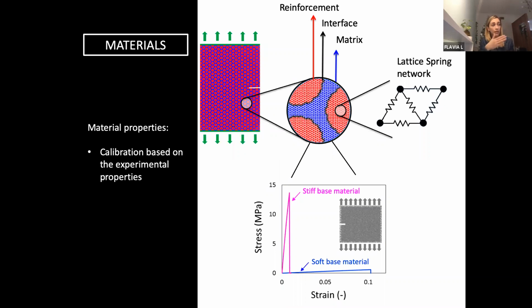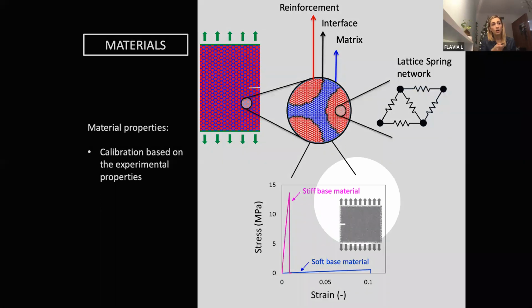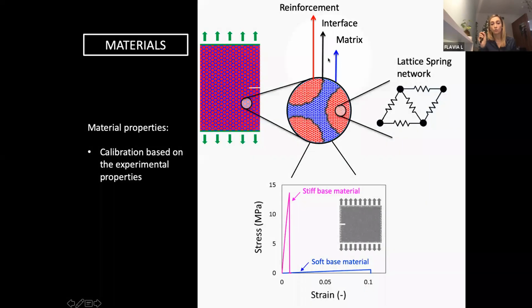First we did a calibration based on the experimental properties, and in particular on the building blocks. So we have stiff base materials and soft base materials. But what is important is that we also have an interface, which actually plays a crucial role here. We noticed that by modeling the interface, the behavior changes completely. So in the calibration, we tried different combinations of reinforcement and matrix to find the best interface values, which could approximate the experimental curve.